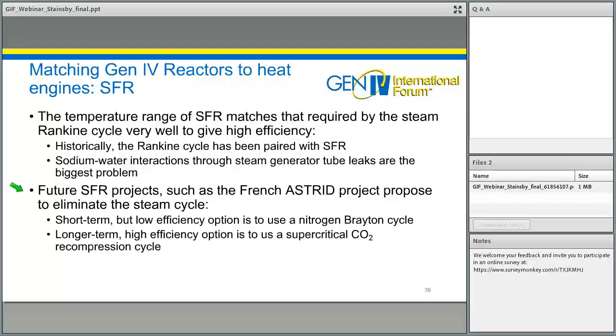The short-term option for Astrid is to actually use a nitrogen Brayton cycle. But as I said before, for a Brayton cycle, we've really got to drive to high temperatures to get a good work ratio out of it. So the Astrid Brayton cycle will deliver thermal efficiency which is actually quite low for a fast reactor. It'll be around 30 to 32%, which is comparable to what you get from a pressurized water reactor, but probably 10 percentage points below what you'd expect for a sodium-cooled fast reactor. But it's the first step.